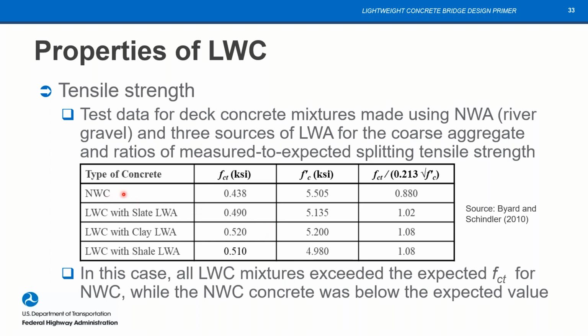Here we have a normal weight mix that used river gravel, and then we had lightweight mixes that used the 3 different types of lightweight raw materials. This is the splitting tensile strength that was measured, the compressive strength, and then the ratio. Oddly enough, if you look at this, and this is essentially the expected splitting tensile strength for normal weight concrete in the denominator. Of these 4 specimens, the only one that came in under the expected for normal weight was the normal weight concrete. All of the lightweight tensile strengths were higher than would be expected had the normal weight concrete equation been used.